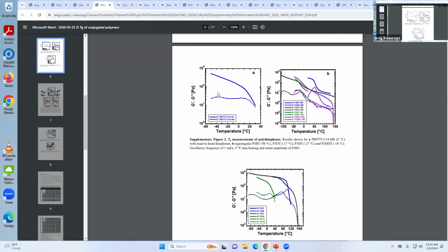that relaxation of that side group is a sizable contribution, and then the TG. And then he finds out, so the crux of this whole paper is that he has a side group that's short, and then the TG. So these two relaxations, side group TG, main chain TG. And then if he makes a side group longer, that relaxation goes to a higher temperature. And at the same time, the TG relaxation moves to the left. So they start to merge at some point, right? So the two things are not independent. The side group, if it gets long, plasticizes the TG and shifts it to the left.